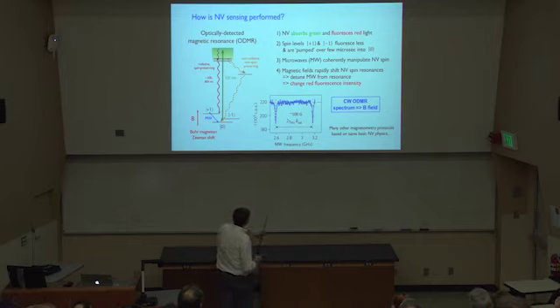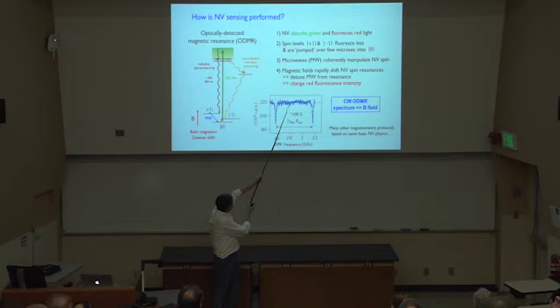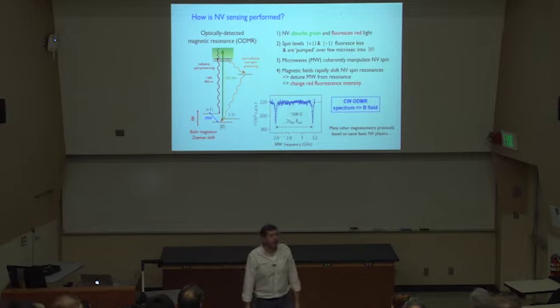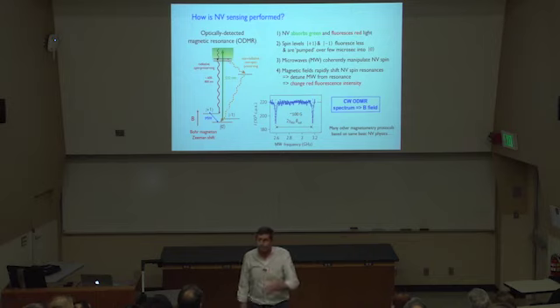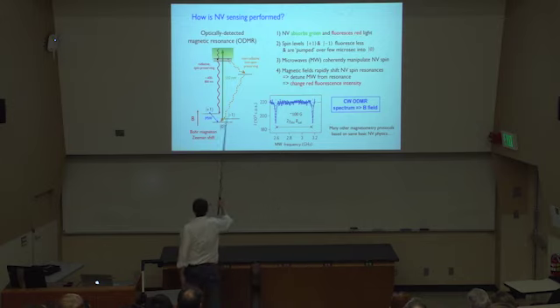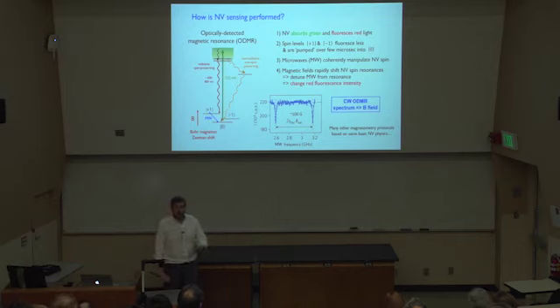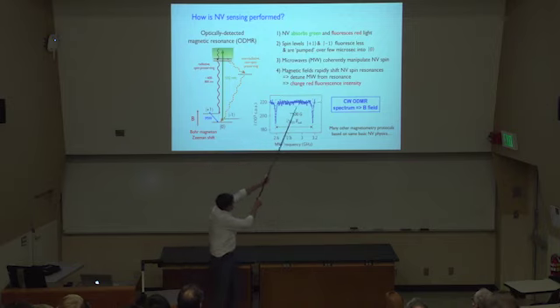So let's imagine you decide, I like 2.8 gigahertz. I'm going to be far off resonance from any of these, either the ms equals 0 to minus 1 or 0 to plus 1 transitions. I like 2.8 gigahertz. And I also like 2.81 and 2.79, and I'm moving around in there. What you're going to find is the intensity of the red photons doesn't change with microwaves, of course, because the microwaves aren't doing anything. But as you go onto one of those spin transitions, either this transition or this transition, here and here, you have a competition between the optical pumping induced by the green photons and the decay pathways and the spin changing nature of the resonant microwaves. And so you get a sharp dip and another sharp dip in the intensity of red photons coming out because of this competition.